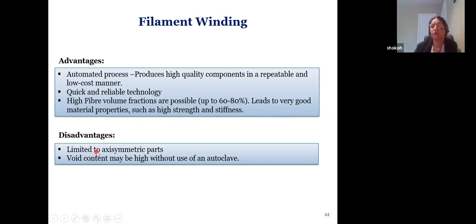Disadvantage, you can do this process only on symmetric parts because of the way we do it. And void content, which is the air bubbles we try to get rid of, is high in this. You have to use an autoclave to make sure this is gone, or another way to remove that. So that's a disadvantage.